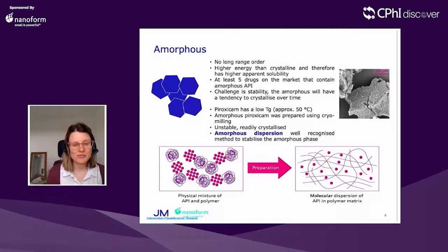Another route to targeting a higher solubility of an API is to look at an amorphous phase. An amorphous phase has no long-range order. The molecules are orientated randomly in 3D space. And as an amorphous phase is higher in energy than a crystalline phase, we'd expect to see a higher apparent solubility. So we can look at developing an amorphous API on its own without any excipients. In fact, there are at least 5 drugs on the market that contain amorphous API in this way.